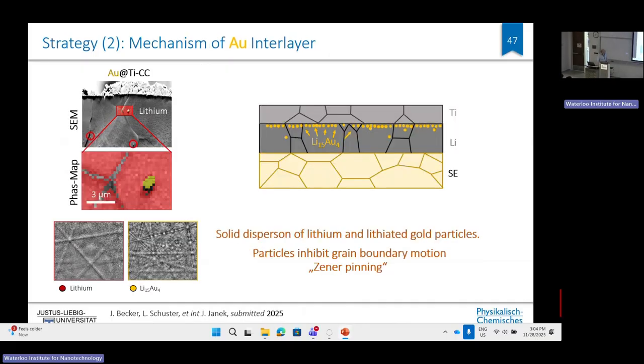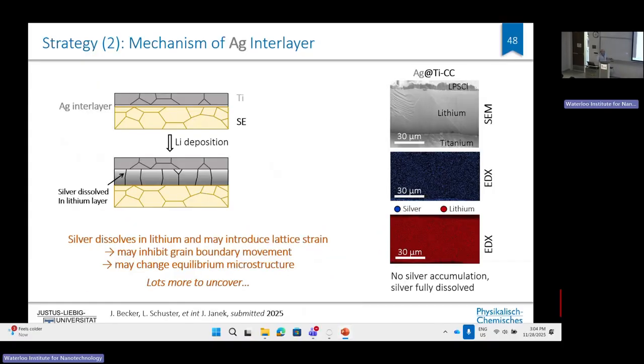Interlayers can control microstructure. In the case of gold, we even have, I would say, a hypothesis, because what we saw is out from the gold interlayer, little lithium-15 gold-4 intermetallic phases, little particles grow, and we think that they really pin the grain boundaries and they can't move anymore. So again, I would say this is electrometallurgy. You dope during plating and you get the dopant back if you strip the lithium, which is, I think, quite nice. The case of silver, it's completely dissolving in the lithium. There must be another effect which we don't yet understand.